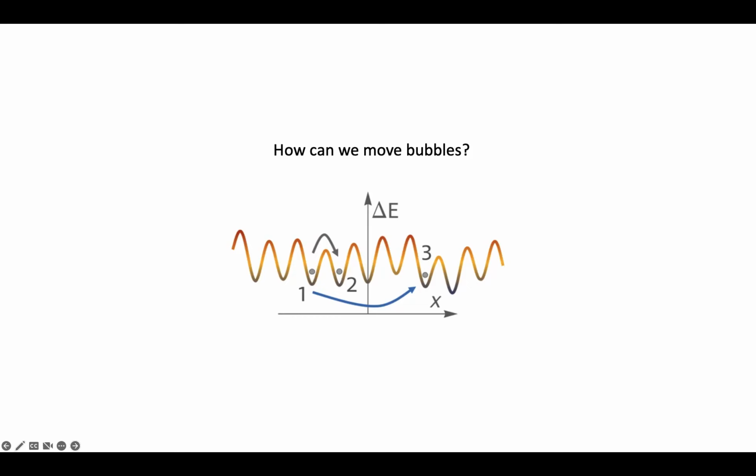Yeah, so of course, the size of the bubbles depends on many different things, for instance, the thickness of the film and the value of the compressive strain. The size of the bubble can be managed. But it's important to see the difference between a bubble and a cylindrical domain. A bubble is a very tiny cylindrical domain, if you want, which actually allows all those things.